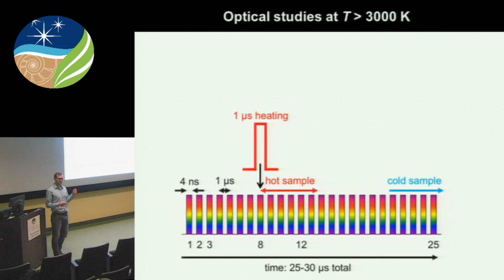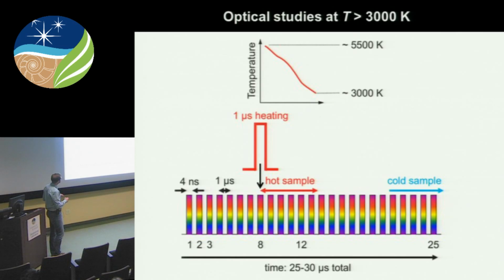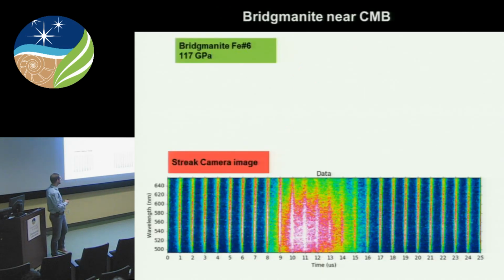However, we do want to study samples even at higher temperatures than 3000 Kelvin, and this is what we do for that. So we time our white lasers a little bit differently in these experiments. Now we have only 1 microsecond between the pulses. And we trigger the heating laser for just 1 microsecond. So we heat our sample for a millionth of a second. And in that time, its temperature shoots up to approximately 5,000 to 6,000 Kelvin, and then it cools off to approximately 3,000 Kelvin in a matter of a few microseconds. And then it remains cold, essentially.